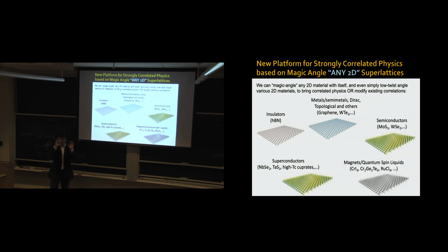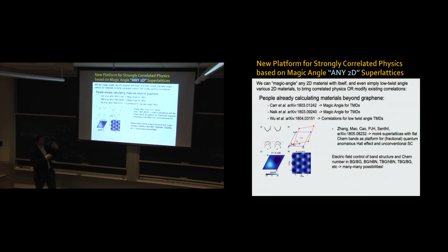So now there's a booming field, and several different material classes have been found that when you twist them at low angles, they exhibit superconductivity and correlated insulating behavior. There are large material classes and theories calculating magic angles for all materials, correlations for various twist angles. This brings together the 2D materials community with the strongly correlated materials community. These flat bands that form in the systems are often topological - they have finite Chern number. So the topological physics community is also coming together in this system. It's very rich, with many, many possibilities.